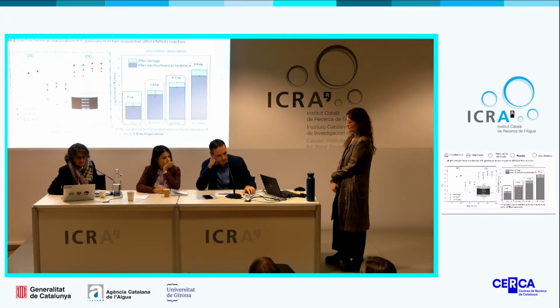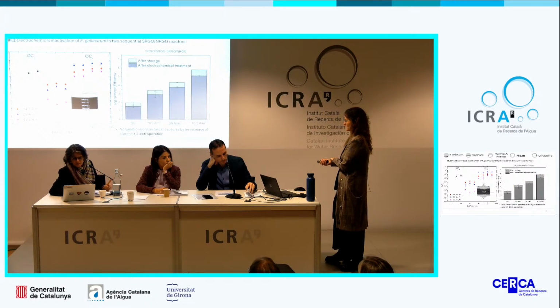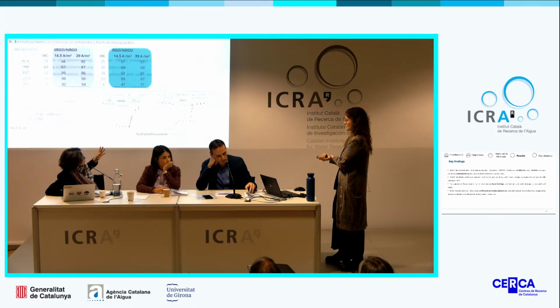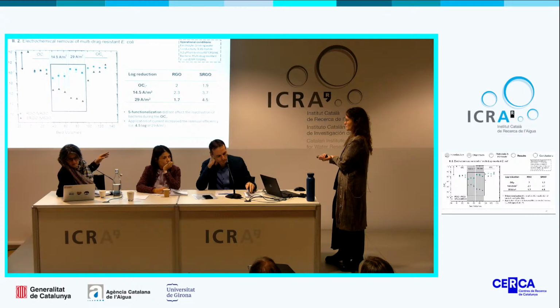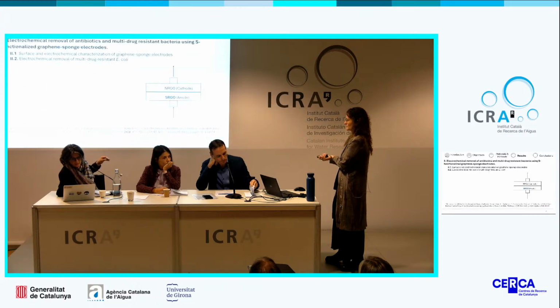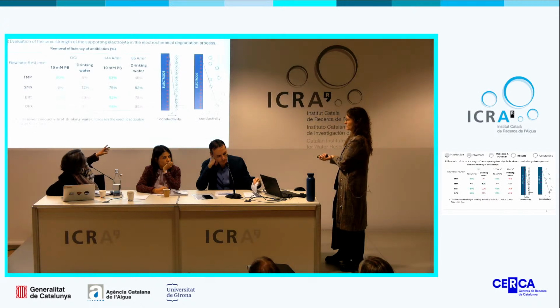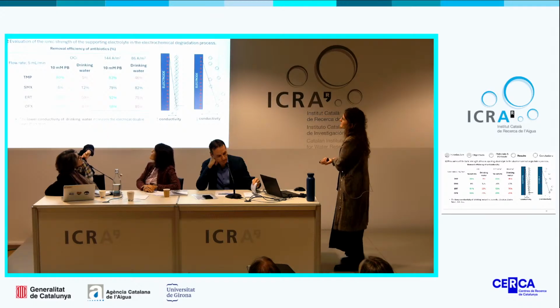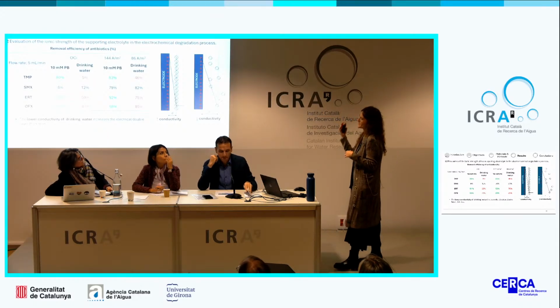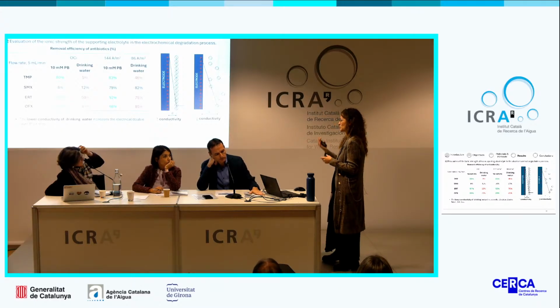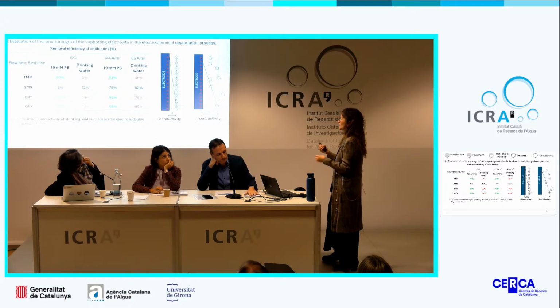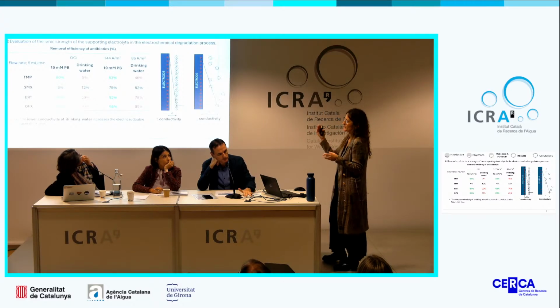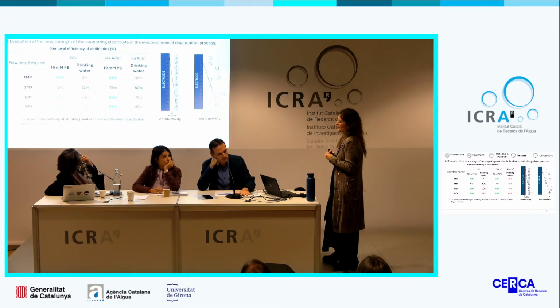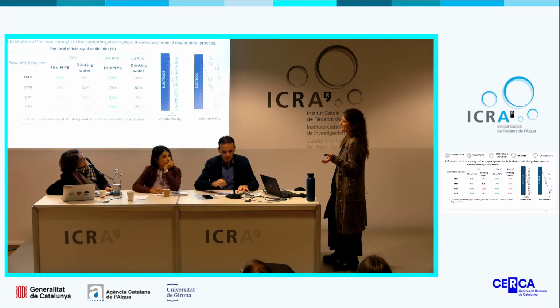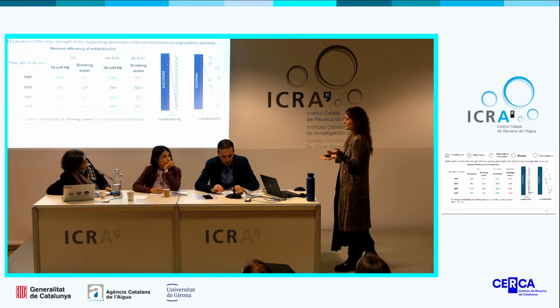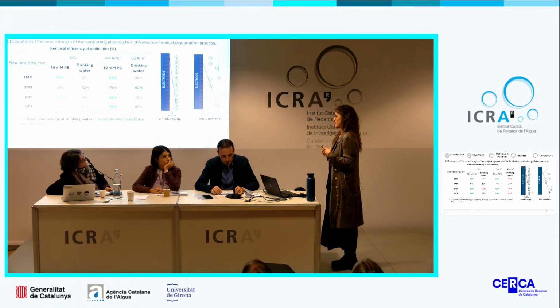Yes, on slide 18, regarding the comparison of the removal of antibiotics in drinking water and buffer solution, yes, the applied current densities were not the same. We couldn't go higher because of the bubble formation and the low conductivity in water. We had a lot of bubble formation, and that's why we just went to the highest current possible, but it's not the same as the phosphate buffer, because since the conductivity is half of it in the case of drinking water, we are producing more bubbles and the system is more resistant.